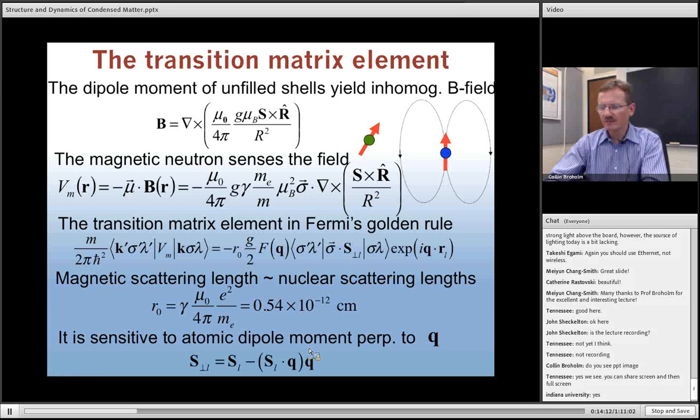But in the case of X-rays, these are very, very weak cross-sections compared to the charge scattering cross-sections. Doesn't mean it's not a very useful and very powerful technique, but it's quite marked that in neutron scattering experiments, these magnetic cross-sections are really very pronounced and will be very noticeable as soon as you put a material in the beam which has magnetic properties. You will begin to see scattering associated with that.